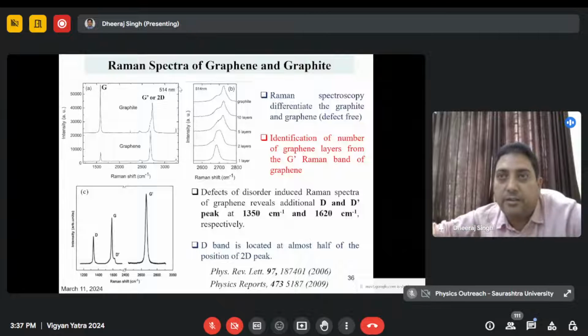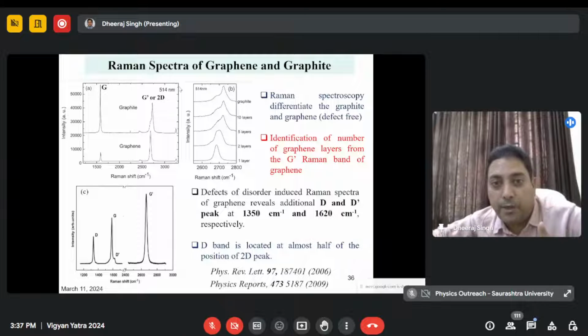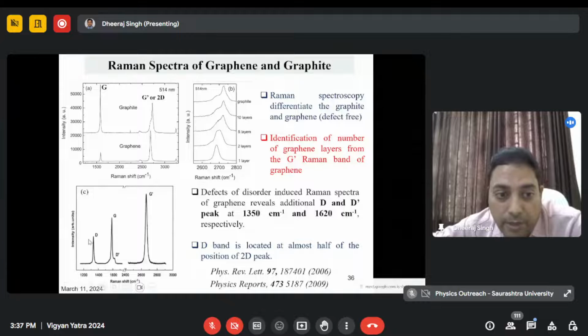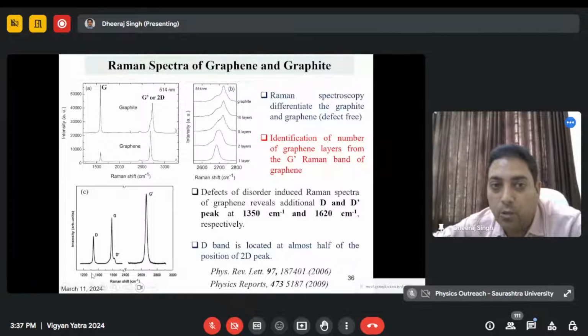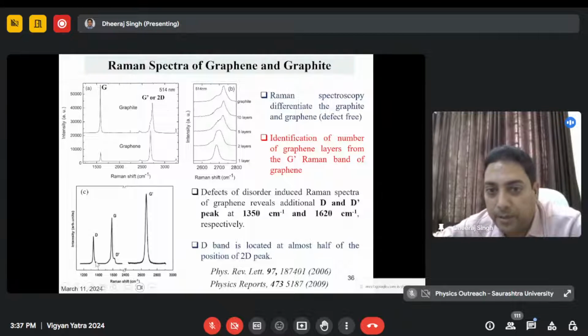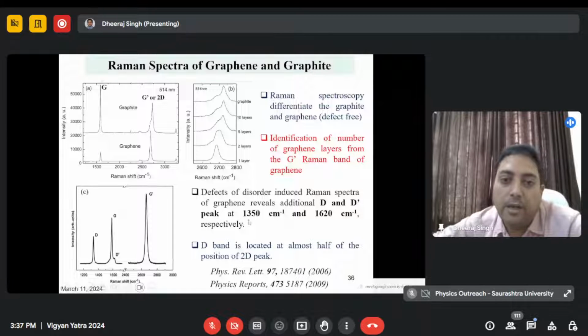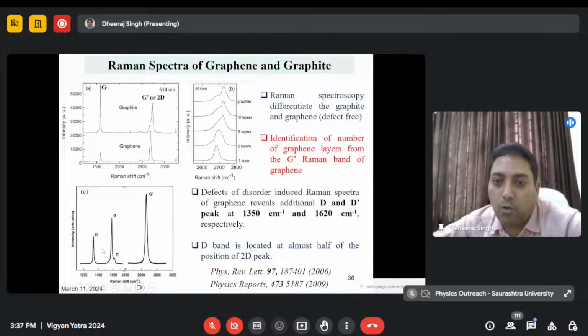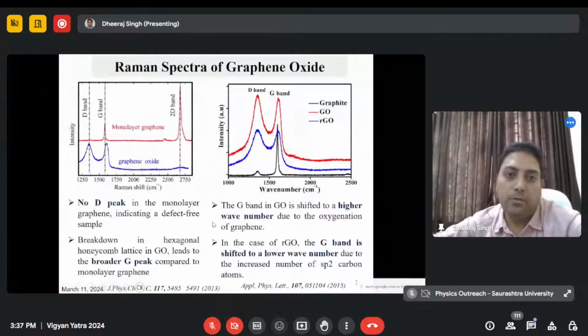Suppose this graphene is a single sheet of graphite. Now if you make any small folding in graphene, it means you are going to deviate your sp2 hybridization into sp3 hybridization. Any such deviation, in terms of D band peaks, will be observed in your system at 1300, something like that. So defects are disorder-induced Raman bands. D and D dash bands are coming at 1350 and 1620 centimeter inverse. So the D band is located at almost half of the position.